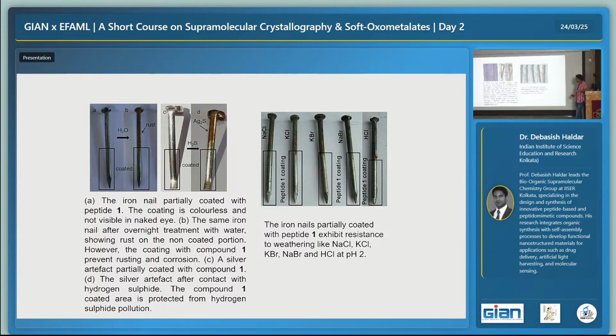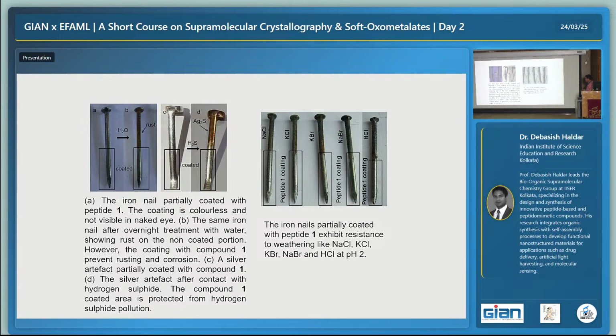So we have covered this silver article again with our material, and now we use it inside a hydrogen sulfide chamber, but nothing happened with the covered area. So you can protect your ornament from silver sulfide formation. We have even tried in very harsh conditions, like putting it in sodium chloride, potassium bromide, even in HCl. When it is coated, there is no corrosion in HCl, but the uncoated part is corroded with HCl. So we think this compound is very effective to protect materials from corrosion.